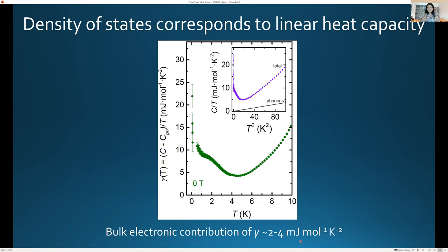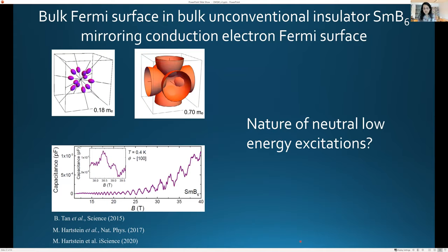Okay, so this is just a summary slide for the samarium hexaboride. And if I didn't tell you anything else about this material and I just showed you these oscillations, one could come to the conclusion, yep, this is consistent with a metal with this Fermi surface and light electron masses, which is consistent with a conduction electron Fermi surface. What is the conundrum here is that the electrical resistivity is consistent with that of a good insulator. So where are these oscillations coming from?